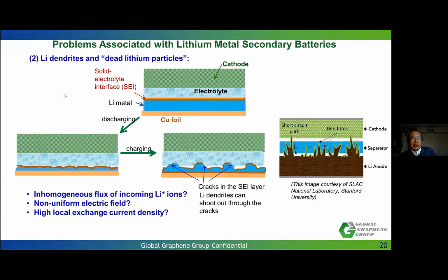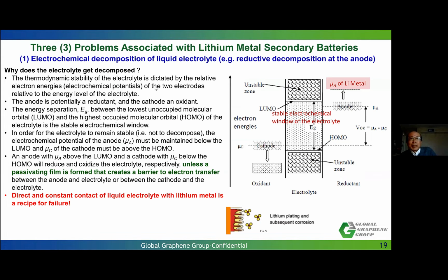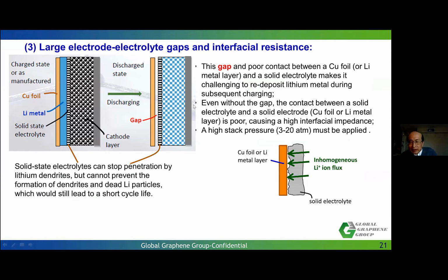The number three is that if you have, for example, your lithium metal on your anode, and then during discharge the lithium metal dissolves and goes to your cathode side, you will create a gap here. And so typically in industry, you will apply a very high holding pressure to your battery stack, and that is really undesirable.